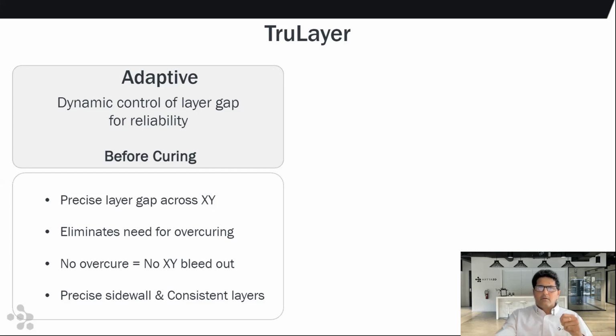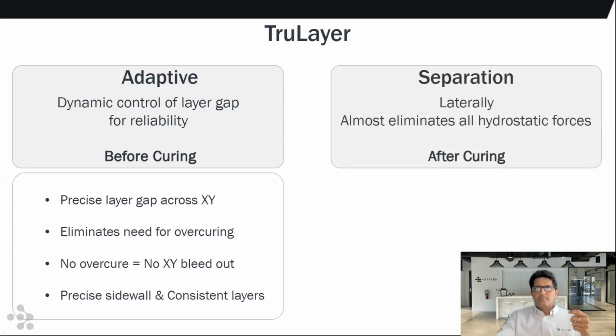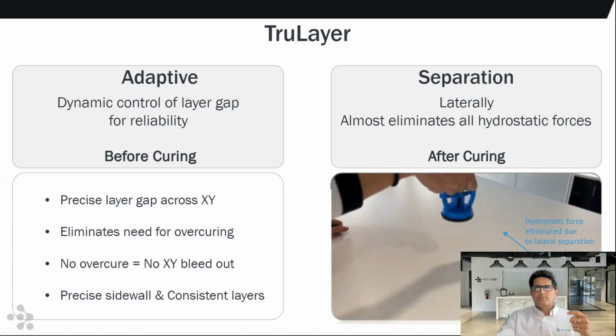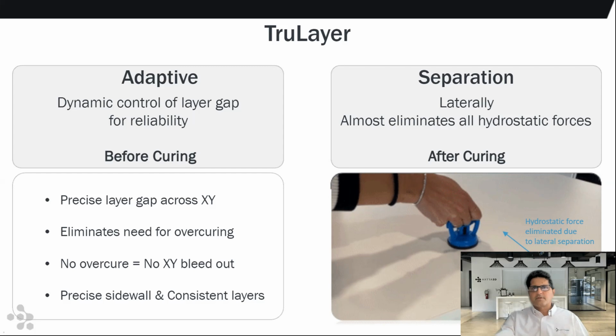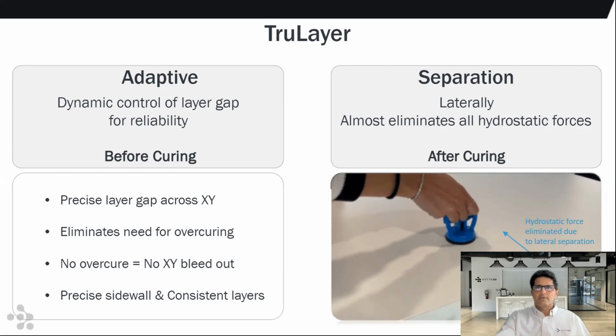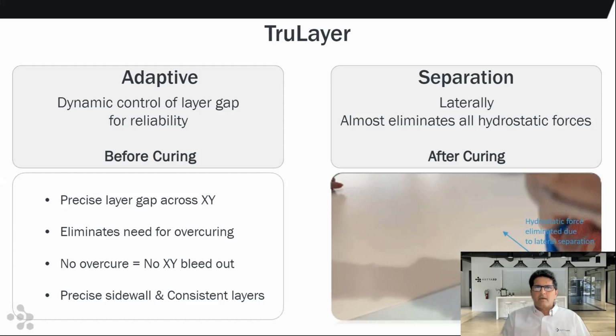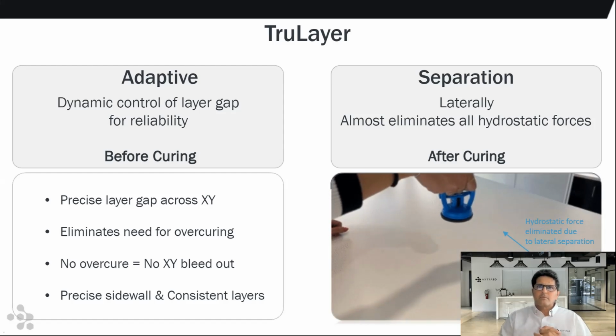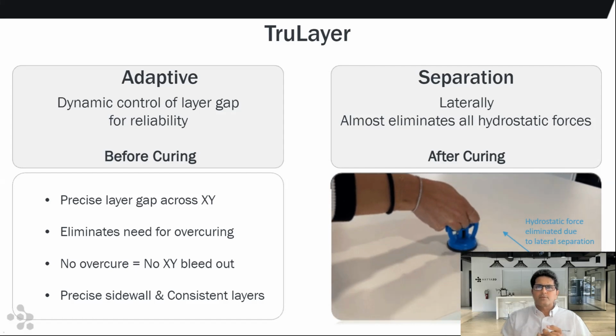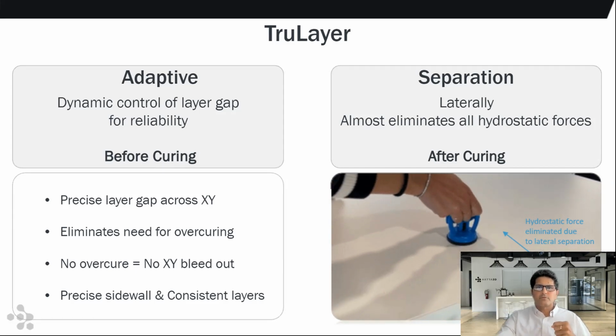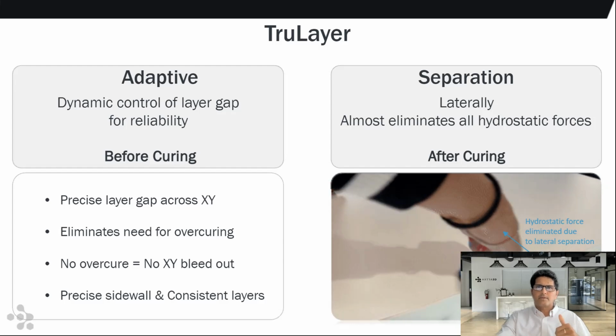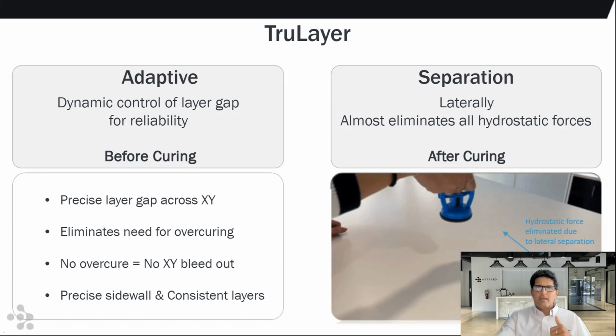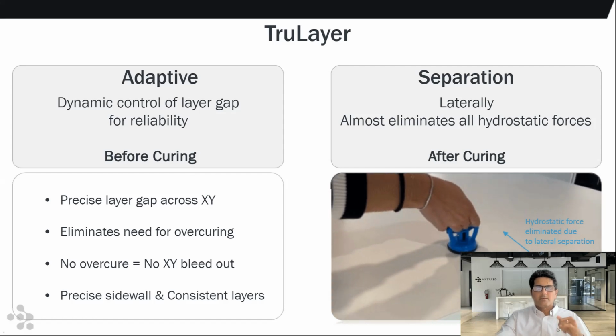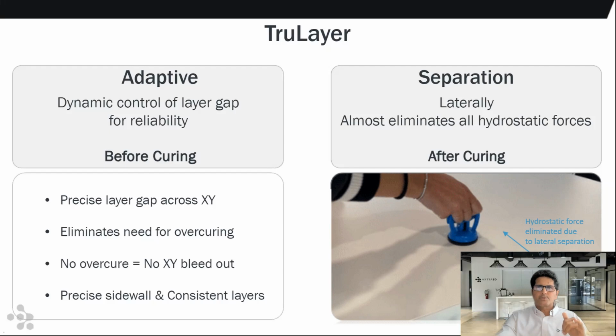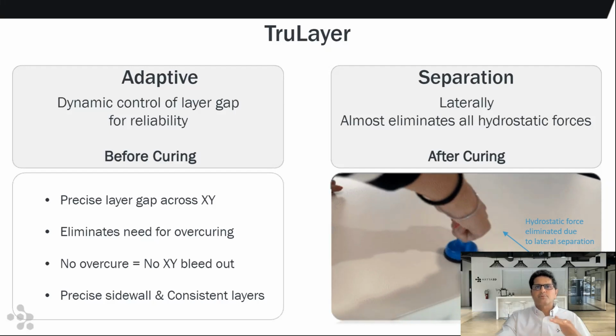Now, once the gap is adjusted, as we saw in the previous slide, there were vertical suppression forces that created hydrostatic forces. In our case, we came up with what we call TruLayer separation. TruLayer separation is, instead of vertical separation, we separate the part laterally from the film. And this almost completely eliminates the hydrostatic forces, yielding a very pristine layer.